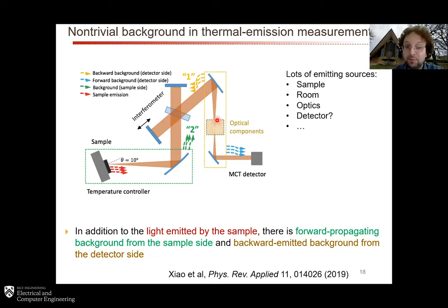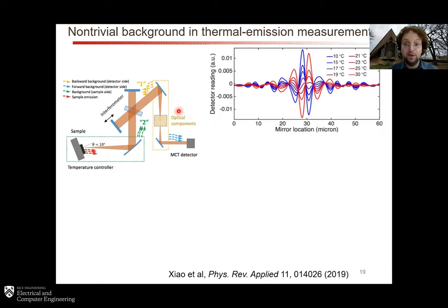So they were thermally emitting in the backward direction, and then this light would bounce off the interferometer, make it all the way back, and make it into the detector. And so it turns out that this negative propagation contribution is what causes this apparent decrease in the signal as you increase the temperature, and then an increase back up again as you increase the temperature some more. So I can show you a little bit more details about how that works.